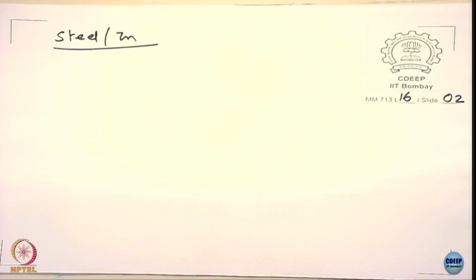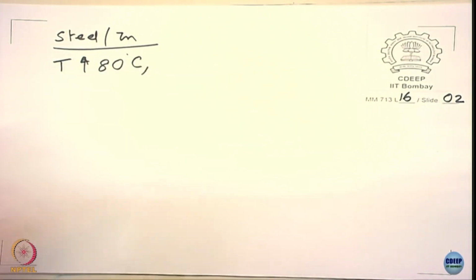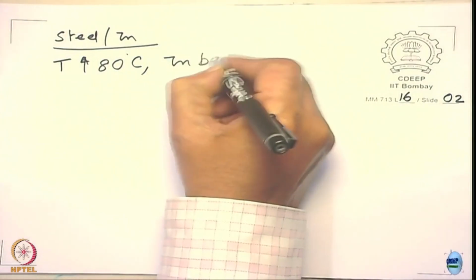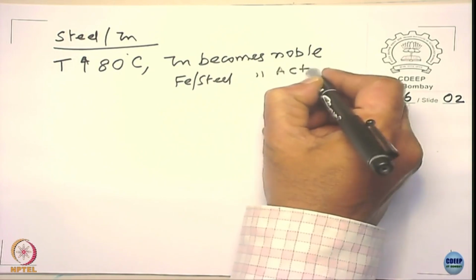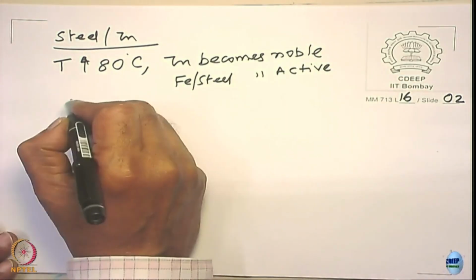Let us take the case of steel versus zinc here. All of us know that galvanized steel, the zinc coating, sacrifices and then the steel is getting protected. But if the temperature goes beyond 80 degrees Celsius, zinc becomes noble and iron, steel, becomes active, and this is called galvanic reversal.